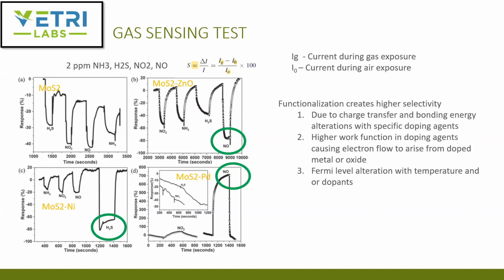And in addition, most of these functionalizations look to alter the way the bonding energy works. So it affects how these gases bond to the functionalized materials. And some of these functionalized materials, for example, palladium with moly sulfide, have a different, higher work function, which also gives them the ability to give electrons more easily than moly sulfide. So it does impact the way the sensor operates. And then in addition, there is a Fermi level alteration that happens, especially when you put nickel and zinc oxide, which is essentially how far in you can dig in for the electrons from the conduction band. So there are a lot of mechanisms that they rationalize for the benefit of functionalization, but the functionalization is definitely unique in terms of which gas you have to be selective to.